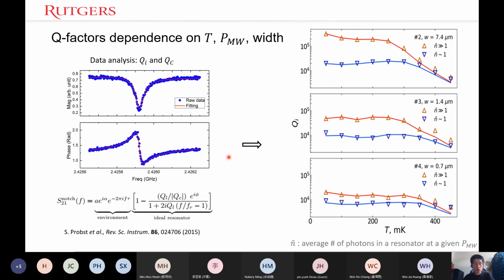The resonance frequency and the losses are measured by sweeping the microwave frequency across the resonance, and by following the very common so-called phi rotation method, we extract the quality factor. It is the internal quality factor that we are particularly interested in, because it tells us how good the film is, what the loss mechanisms in our film are, and whether this is a typical material that we are already aware of.